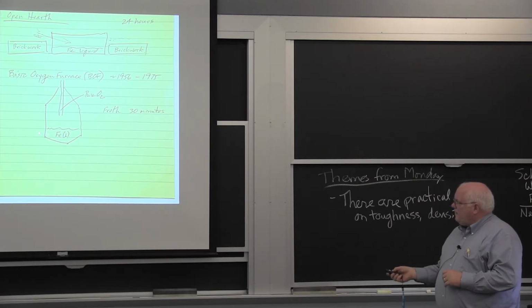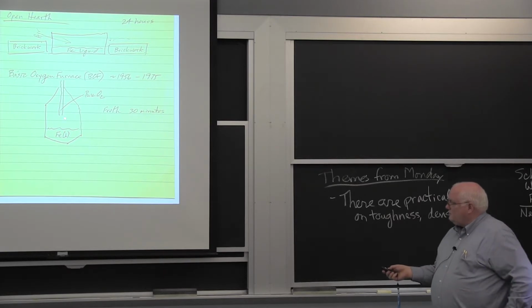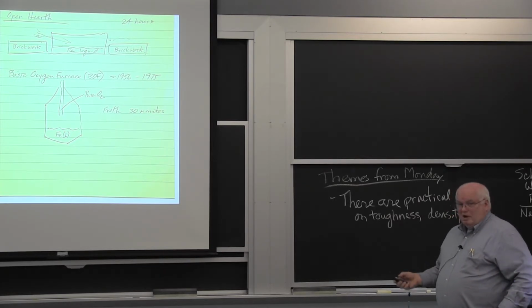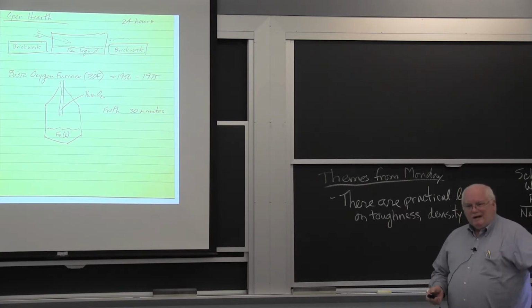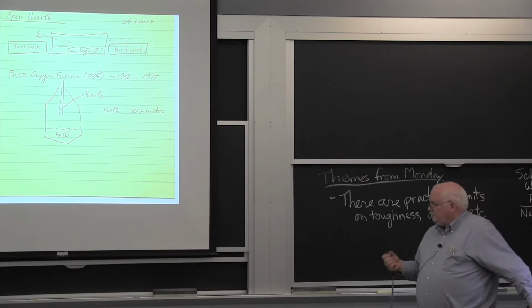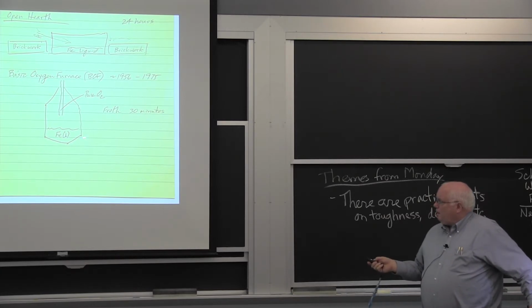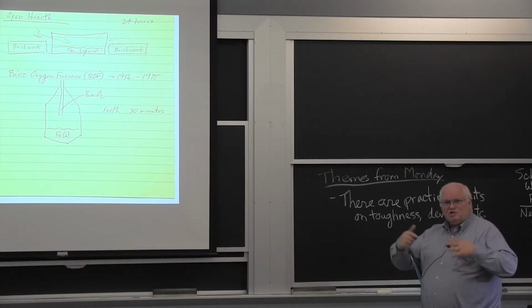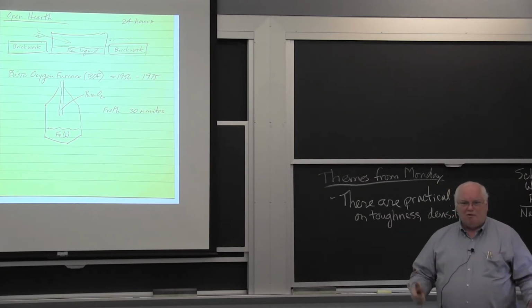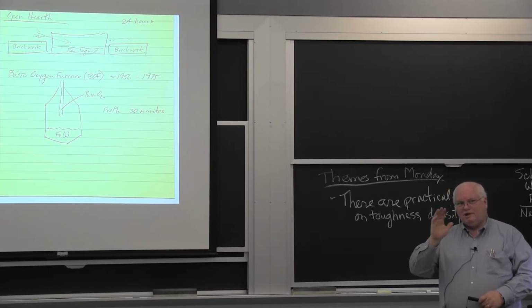Anyway, this thing actually is only filled about 10 feet deep, and it's about three stories tall. And when you actually blow the oxygen in there at supersonic velocity, or sonic actually, it's not supersonic, but at sonic velocity, it's liquid oxygen. An oxygen company will build a plant right next to the steel mill to supply the liquid oxygen. So they do a refrigeration plant, whether it's Linde or Air Products. You'd have a company that would build a plant right next to your steel mill to be able to supply the liquid oxygen. And this whole thing turns into a froth that's about 2 or 3 stories tall of just molten steel and oxygen just reacting and burning rapidly. It's pretty dramatic to see it from a distance.